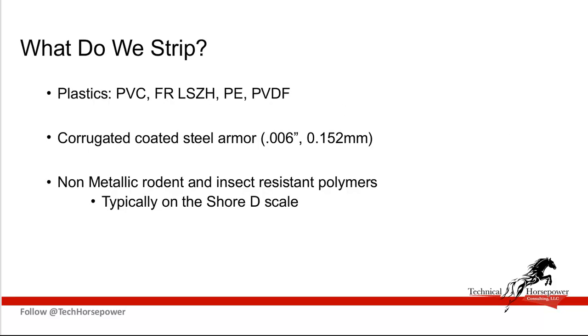And we strip a variety of materials. For years, you had rubber and PVC electrical cables that you were stripping, maybe polyethylene telephone cables. We use a variety of different plastics today, including low-smoke zero halogens, which are many times highly filled, flame retardant materials, PVDF, which is a form of fluoropolymer. They all have different characteristics, but we also strip other things in our cables. We strip corrugated steel armor, if you will, the conventional rodent protection for both copper and fiber cables. And this is typically 6/1000ths of an inch or 0.152 millimeters in thickness, and it's coated on both sides with an adhesive material that sticks it to the polyethylene outer jacket.